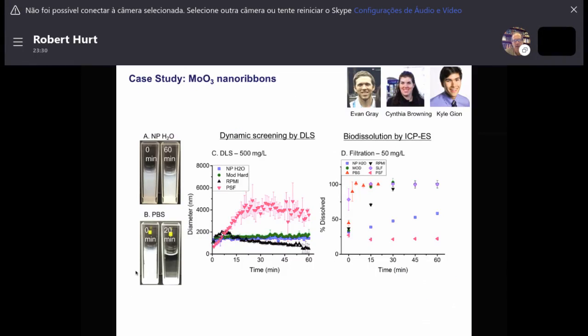But what we found out very quickly, actually, was that these materials, when they're diluted into the kinds of concentrations that one finds, say, in the human lung, or under injection into the bloodstream, or in the GI tract, they seem to dissolve quickly, especially in buffered solutions with controlled pH. And you can see the material in the images going clear after 20 minutes; this white cloudy suspension with these white needle-like molybdenum trioxide nanoribbons goes clear, which suggests to us dissolution in a pretty short time. It doesn't happen in simple water solutions, but it happens in, say, some cell culture media, and it happens in buffers. And the data on the right show that if you measure the amount of dissolved molybdenum over the course of an hour in many media, the ribbons disappear and dissolve.